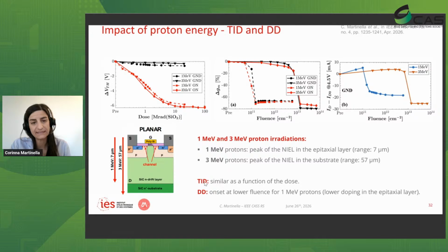So if we look at the TID as a function of the dose, here we have the delta of the threshold voltage, and we see that things are pretty much similar. However, if we look at the results in terms of the fluence, we can see, for example, here, this is the on-state current, and the displacement damage for the 1 MeV proton is happening much earlier in terms of fluence with respect to the one of the 3 MeV protons. And this is because now the majority of defects are created in the epitaxial layer, where there is also a lower doping with respect to the substrate.